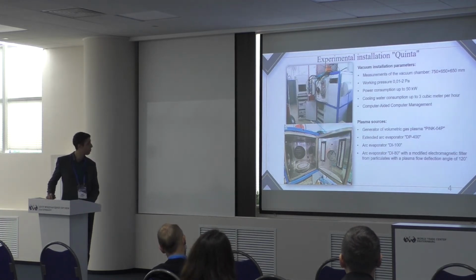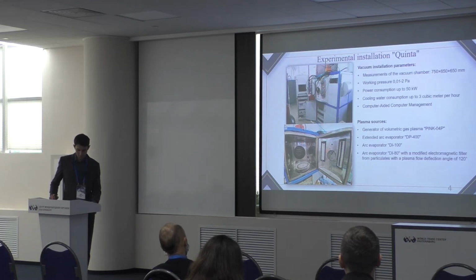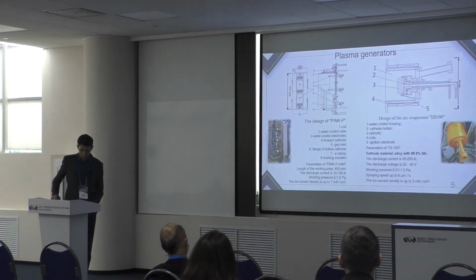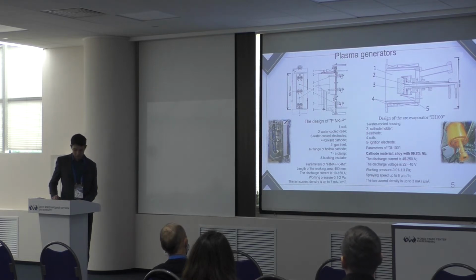The research was carried out on a vacuum ion-plasma installation, Quinta. It has 5 plasma generators with different construction, and a computer control system which allows reproducing the thickness and composition of the layers. For ion plasma nitriding, for ion plasma assistance in vacuum arc deposition of the coatings, a generator based on a non-self-sustaining arc discharge with a thermionic and hollow cathode pair was used.